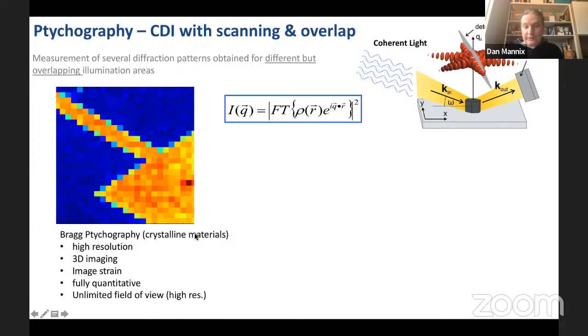First of all, it's very powerful to study crystalline materials because you study Bragg peaks. It has a very high resolution, which goes beyond the beam size. So we're not limited to beam size anymore; we can go below the beam size in our spatial resolution. In principle, it can give 3D imaging. All of these maps that I showed before were just 2D images. In principle, we can get 3D imaging by doing rocking theta scans at a Bragg peak. You can also image strain in Bragg, which is great because then you can correlate strain to what that's doing to magnetism, in principle, if you could develop magnetic Bragg ptychography.